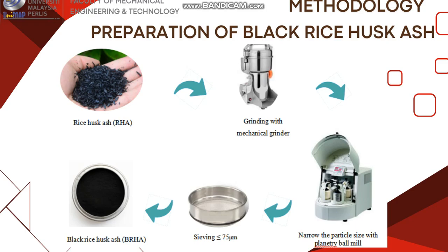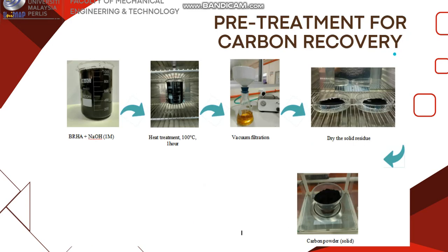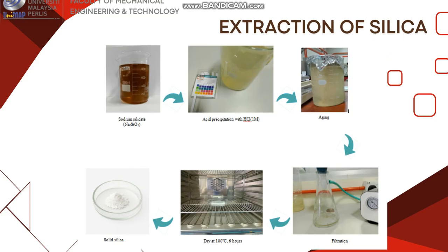Experimental procedures. The experimental procedure includes preparation of BRHA, with a schematic diagram showing grinding, sieving, pre-treatment for carbon recovery, chemical extraction using sodium hydroxide, and extraction of silica, precipitation with acid and aging. Each step plays a critical role in achieving a high yield of pure silica while minimizing environmental impact.